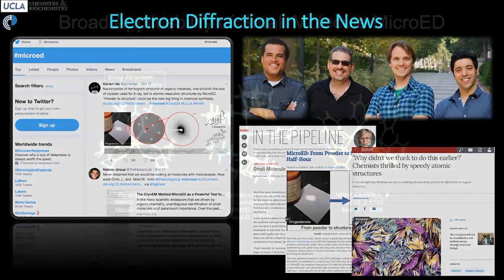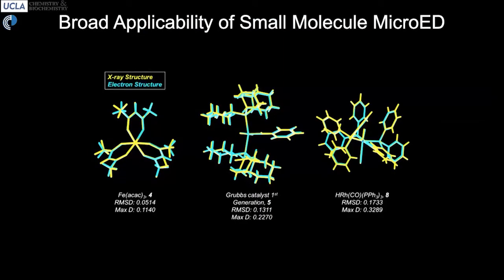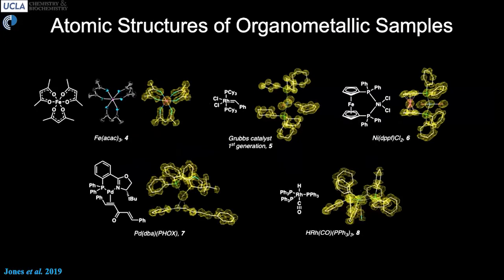What we've learned is that the structures determined by this method are relatively accurate, or at least we believe as accurate as the types of structures you would determine from much larger crystals using canonical X-ray diffraction methods. We're really excited that you can take canonical X-ray diffraction methods that work best with larger crystals and apply them to tiny, tiny crystals. These are crystals on the nanoscale, and you get structures that are almost as accurate. This was borne out by collaboration with Professor Jose Rodriguez, who is also involved in BioPACIFIC and has led a good portion of his group in the application of electron diffraction techniques to complex small molecules.